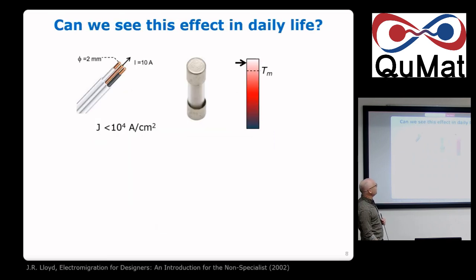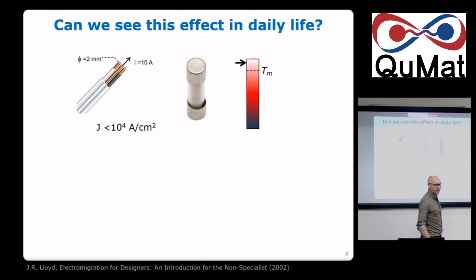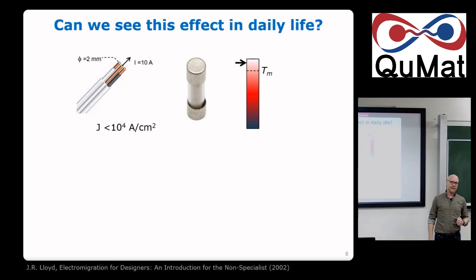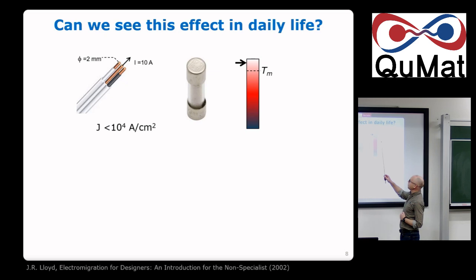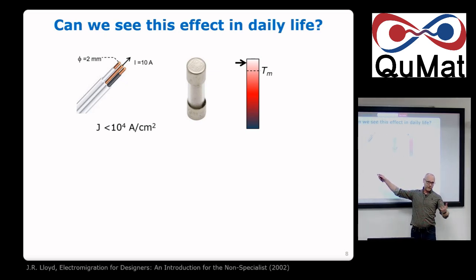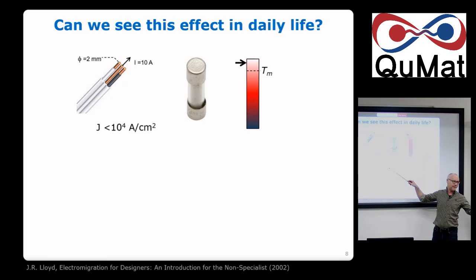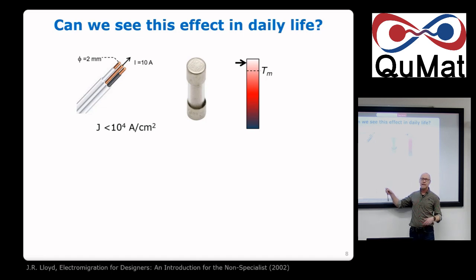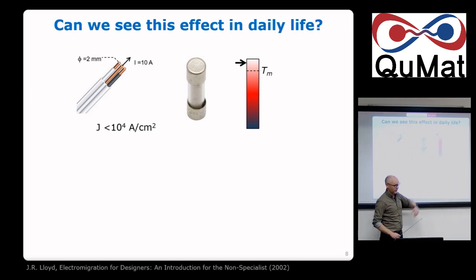Okay. So the first question is, why do we never talk about this? Why don't we see this in real life? The reason is, if you go to house appliances or electrodomestic things, once you reach a current density of 10 to the 4th amperes per square centimeter, the temperature of your wire goes above the melting point. You just melt the material. So the current density can never go really high because you cannot evacuate the heat, as simple as that. So that's why you will never see electromigration in normal wires. Let's say that's how a fuse works.